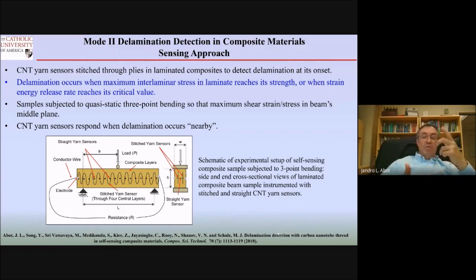I said, well, I was working with composite materials at the time. You probably know composite materials are used in planes, used in space applications. They're very light, they're very stiff, they're very strong, right? The only issue with composite materials, one of the drawbacks, is that they're laminated materials. And when you pull in the transverse direction to the laminate, the materials delaminate, and they get damaged, and you don't see the damage, right?